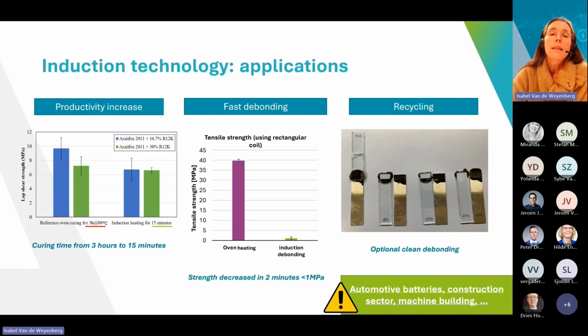And also a nice possibility is that when you have the right surface conditions, you can also achieve clean debonding. So clean debonding means that you do not have to scrape off your adhesive residues after debonding. So that's what you see very well at the last sample. This makes it quite an interesting technology to apply in, for example, automotive batteries, construction sector, machine building, in every sector where your speed of production is important, of course, in combination with your debonding possibilities.